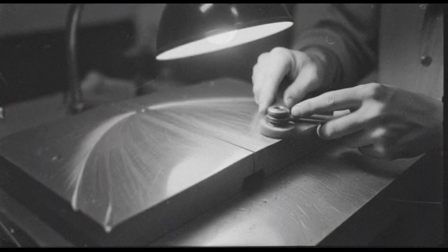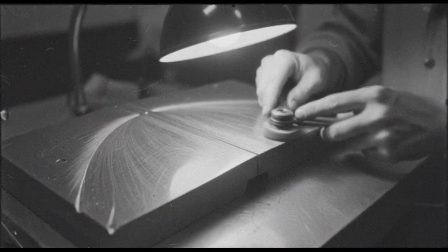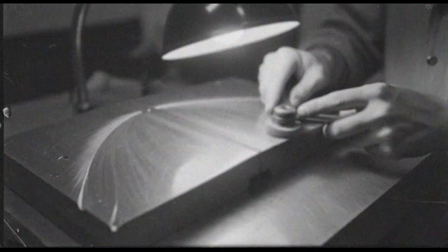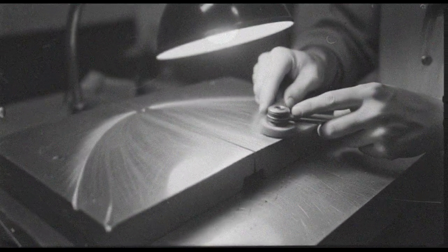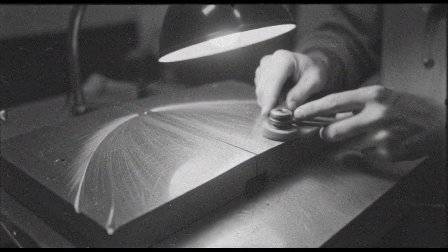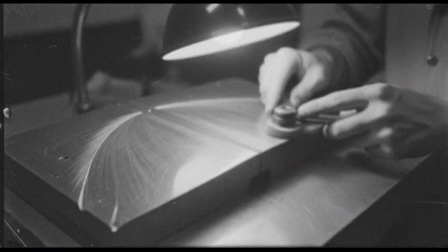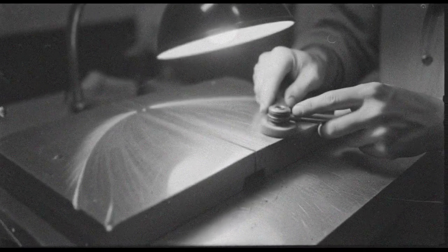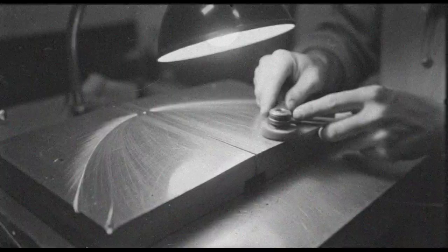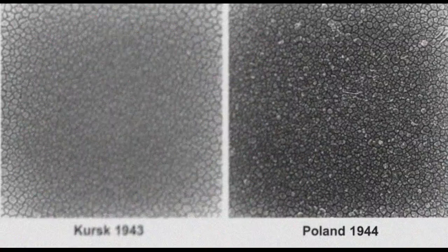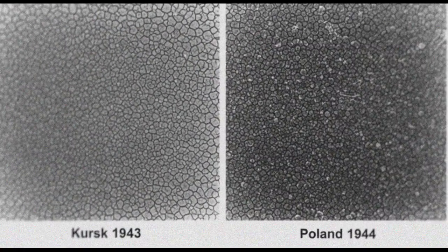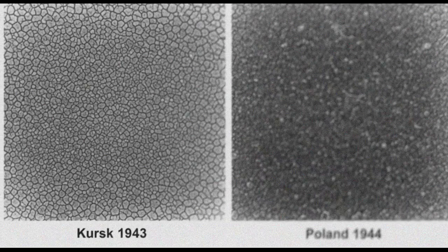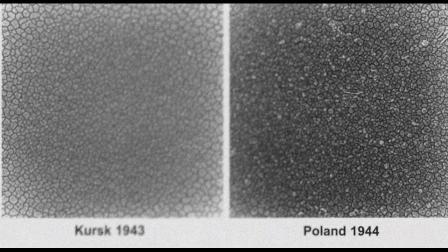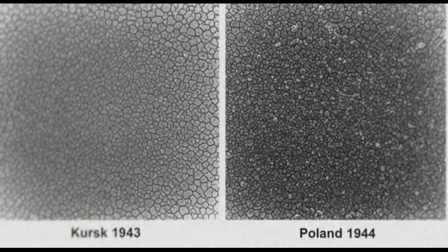The microscopic analysis revealed even more puzzling details. The grain structure was less refined, suggesting the heat treatment process had been different, perhaps rushed or done at incorrect temperatures. More troubling still, the chemical analysis showed significant differences in alloy content. The nickel content was much lower.